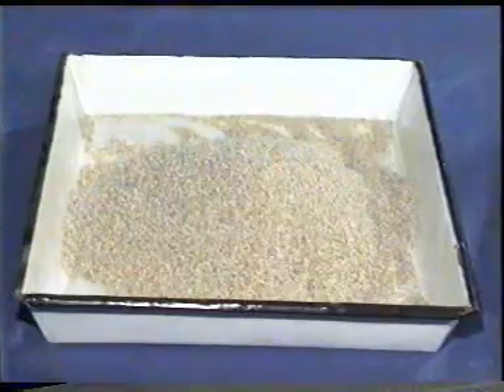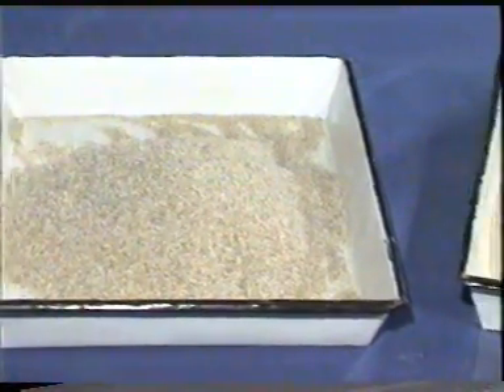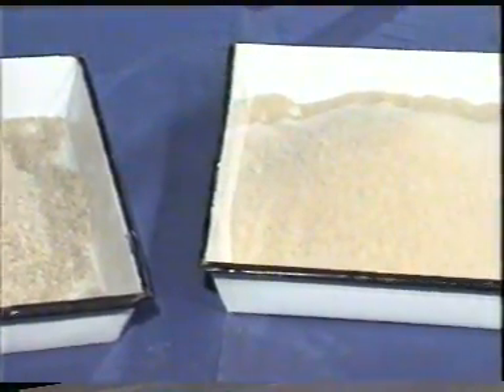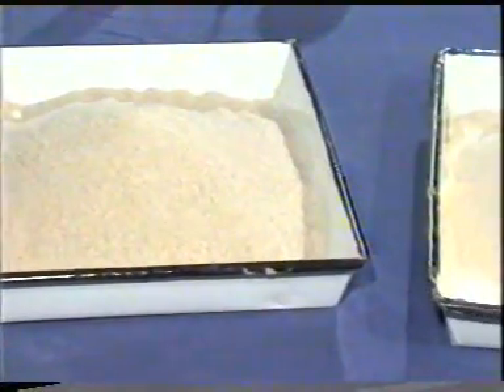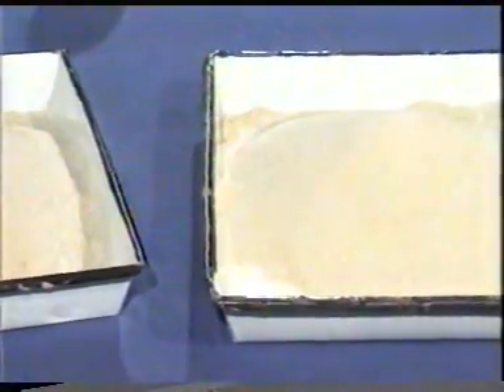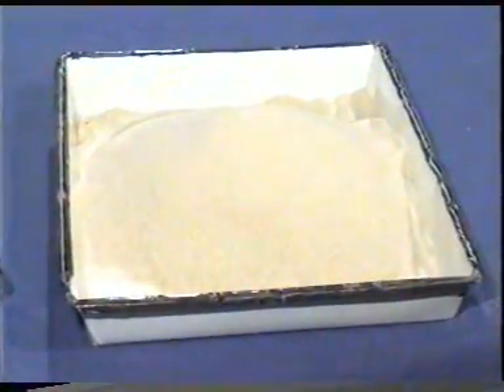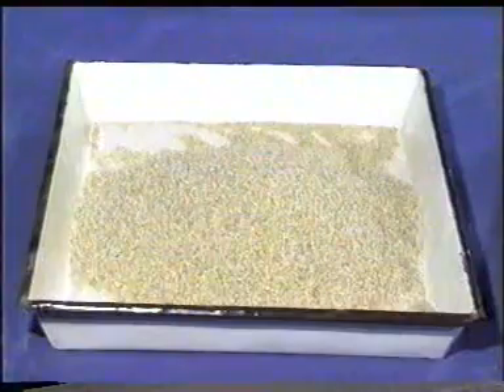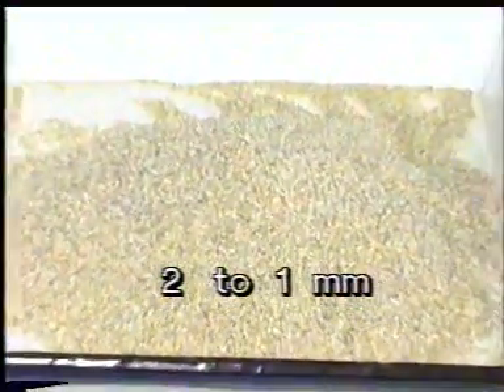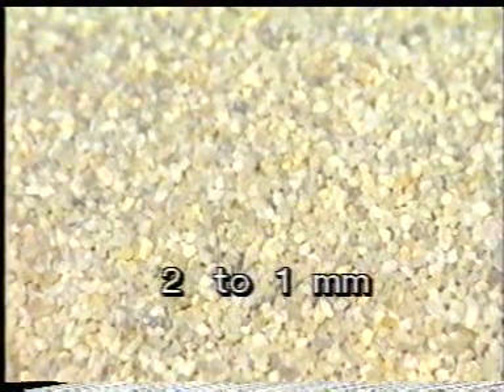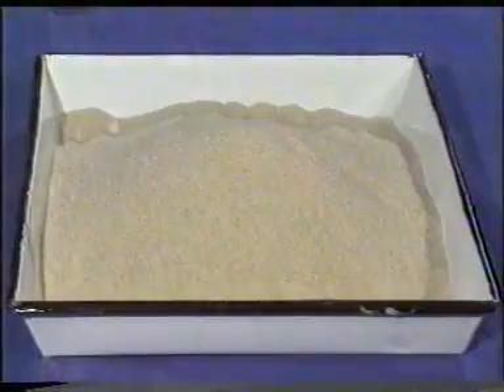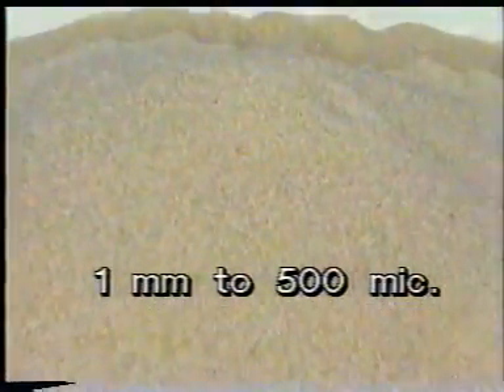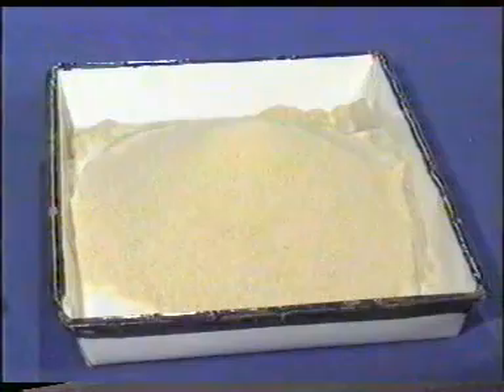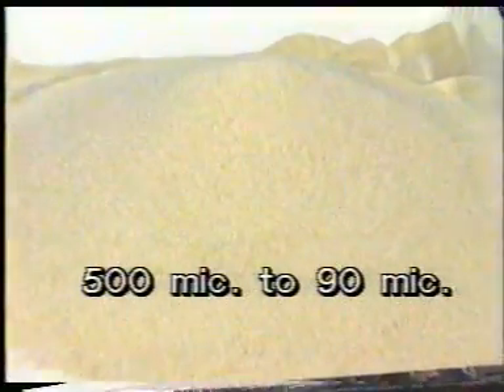The standard sand comprises 3 different grades of sand. The particle size of grade 1 sand varies from 2 to 1 millimeter. Grade 2 sand varies from 1 millimeter to 500 microns, and grade 3 sand varies from 500 microns to 90 microns.